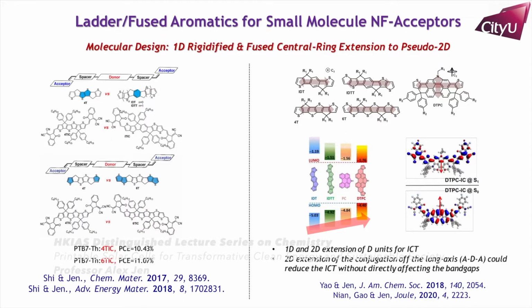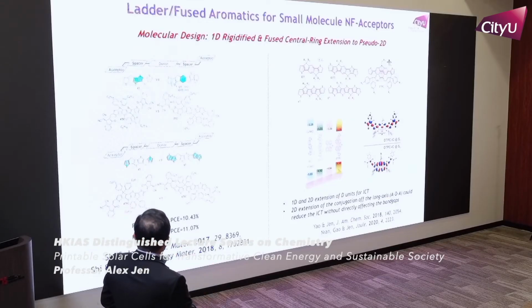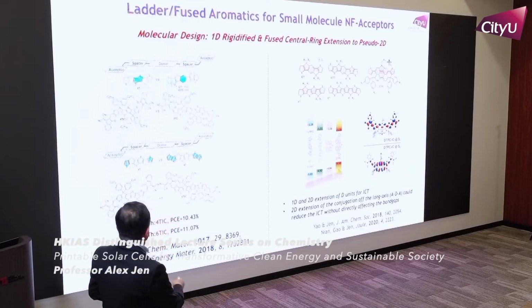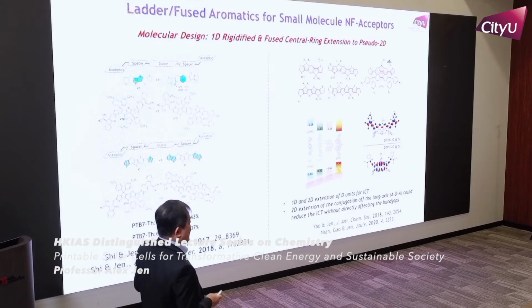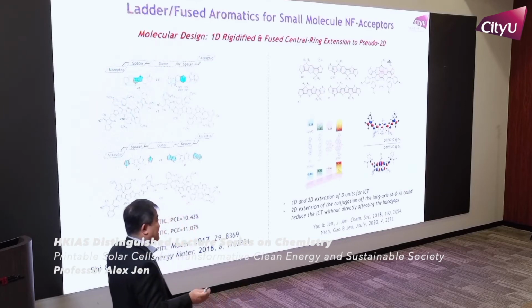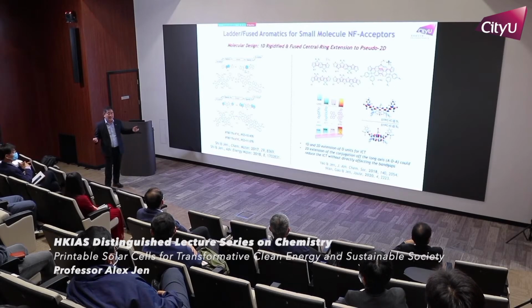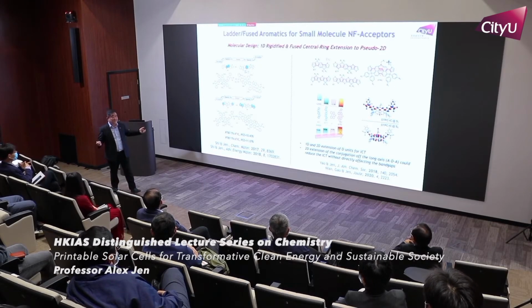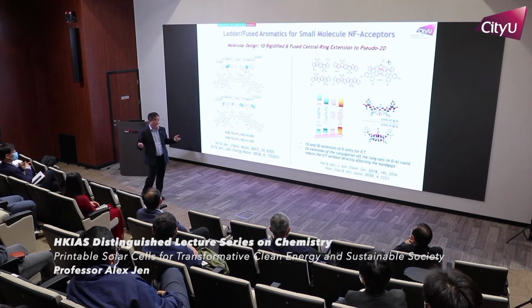In the original design of the non-fullerene acceptor, we're talking about the A-D-A, acceptor-donor-acceptor type of configuration. That's a linear type of structure. But in this kind of configuration, it's relatively difficult to really get a high efficiency out of it because the intramolecular charge transfer is quite strong, and then your fluorescence lifetime is very, very short. As a result, you tend to have a relatively large VOC loss.